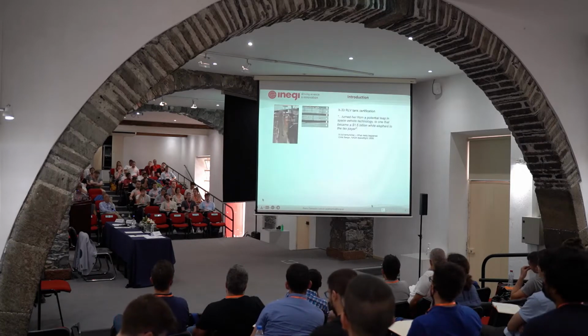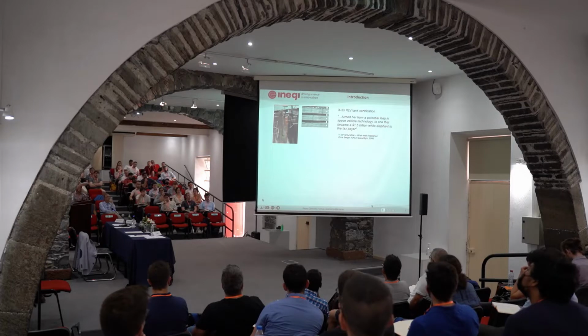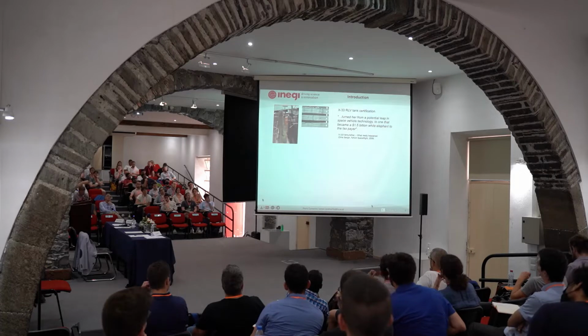The right first time and also the use of these models in failure investigations. What you can see here is the cryogenic fuel tank that was being developed in the early 2000s by Lockheed Martin in collaboration with NASA to be used in the reusable launch vehicle, the X-33. When Lockheed Martin pressurized the cryogenic fuel tank, the tank basically collapsed, and you can see this huge debonding between the face sheet and the core. But the root cause of this collapse was actually these transverse cracks that developed in the composite material that enabled the fuel to leak through the crack. When the fuel reached the core, which was at high temperature, it expanded and applied pressure that resulted in this large fracture.